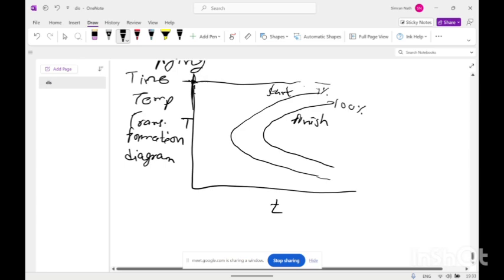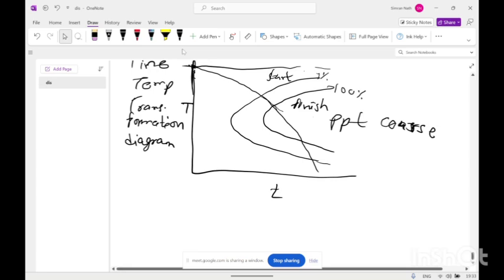If the cooling rate is low, then the curve will follow this path. After crossing this point, the precipitate will form, but it will be coarse, and the coarse precipitate is not required, because coarse precipitate will only precipitate out at the grain boundary region, which will further lead to intergranular fracture.